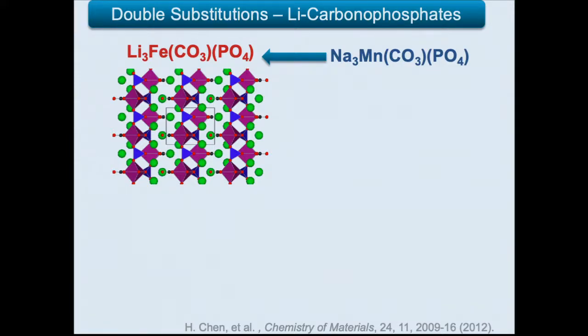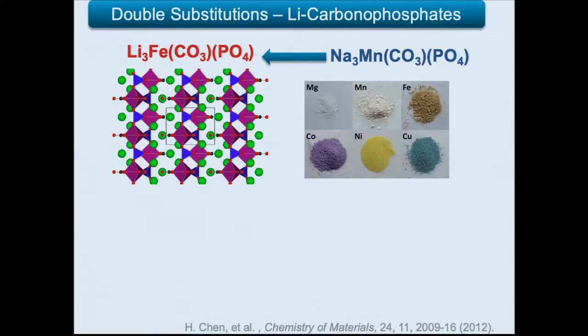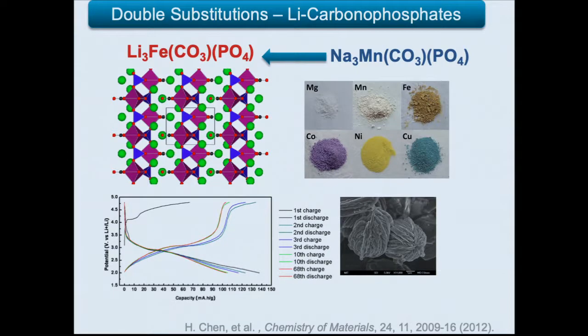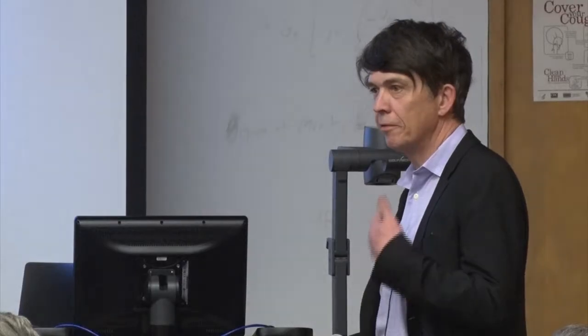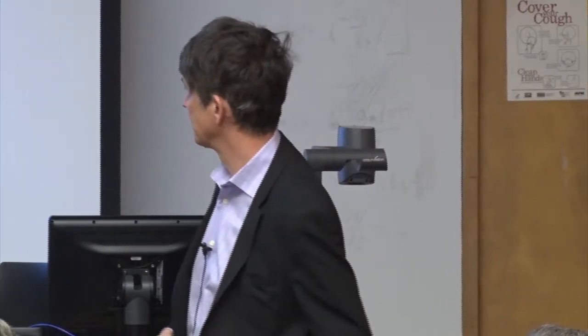This is a double substitution, a very unusual chemistry. These are carbonophosphates. It's a rare combination that carbonate and phosphate groups are combined. This is a natural mineral. It's called sidorenkite. We didn't want to work with sodium at the time. And we did a double substitution, or the computer did one, manganese to iron, sodium to lithium. And again, this is driven by data mined algorithms. And then you calculate its stability. We can now make it with multiple different transition metals. We actually made it in the lab. And you can actually cycle it in a lithium battery. And so these were, again, compounds that were essentially largely independently designed by a computer, by us giving it only a few simple rules to search.